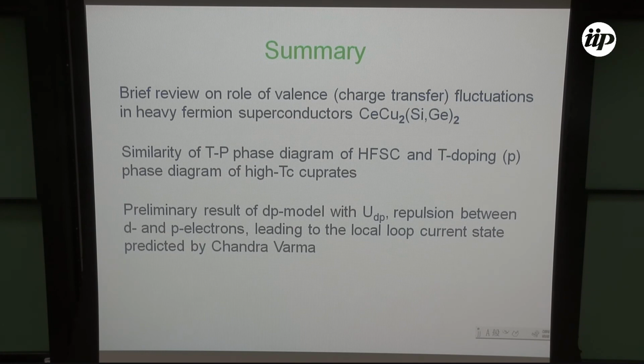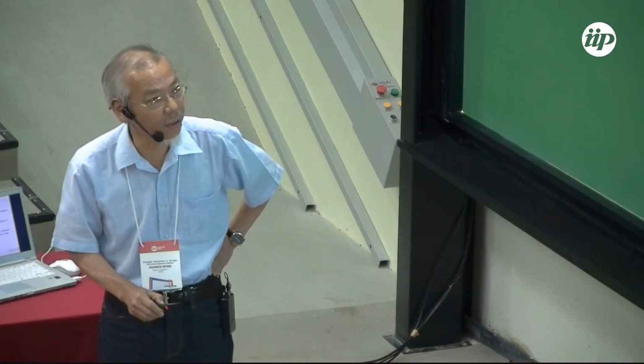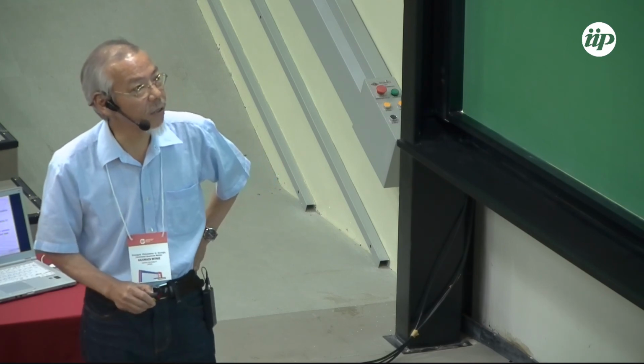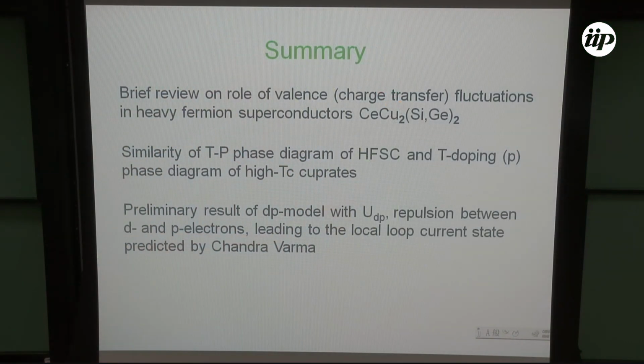So let me summarize. I briefly reviewed the role of valence or charge transfer fluctuations in heavy fermion superconductors, CeCu2(Si,Ge)2, and also the CeRhIn5 case. There, the similarity of the T-P phase diagram of heavy fermion superconductivity and the T-doping phase diagram of high-Tc cuprates is stressed. In the final part, we presented some preliminary results of the dp model with Udp, leading to the local loop current state, as advocated and predicted by Chandra Varma. Thank you very much.